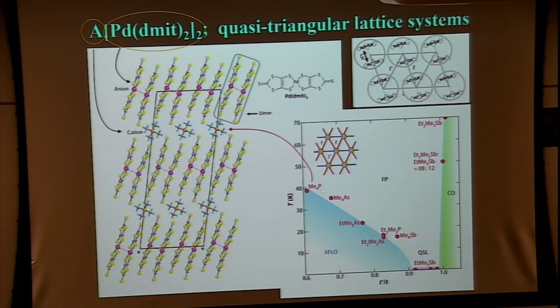So there are methyl phosphorus, methyl arsenide, and many cationic molecules. And this anisotropy, T prime over T, is controlled by this molecular species. If this cation resides in the insulating layers, T prime over T is 0.6 something, so frustration is weak. And you can change the cationic species from here to here. And this material is ethyl-trimethylantimony (EtMe3Sb). This molecule resides in the insulating layers, and this material shows spin liquid behavior.